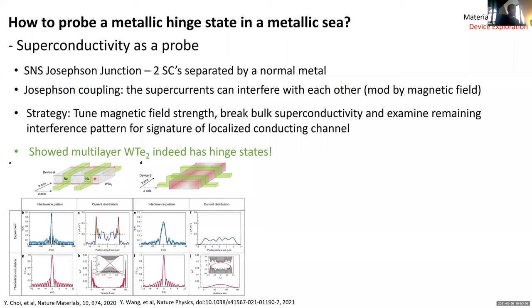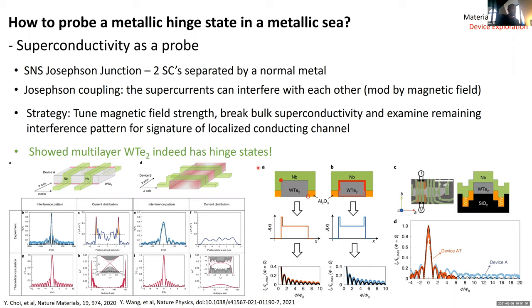But one of the ways we did, since we actually didn't have such easily manipulable magnetic field vectors, is we said, look, if we take our crystal and backfill some way up the sides of the sample with an insulator so that we block contact of the niobium to, let's say, the bottom hinges, it can only contact the top hinges. Then, by theory, the hinge states were only expected to exist on certain hinges.